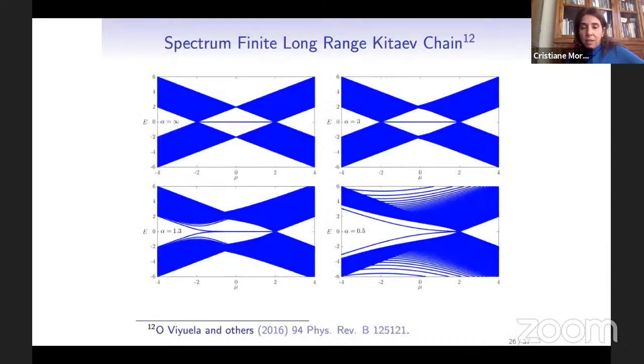And indeed, now you calculate the spectrum for the finite long-range Kitaev chain. If your alpha is infinity, you have the short-range Kitaev chain. You see the topological phase here with the Majorana zero modes between -2 and 2. If you come down to alpha equals 3, things are still very well behaved.